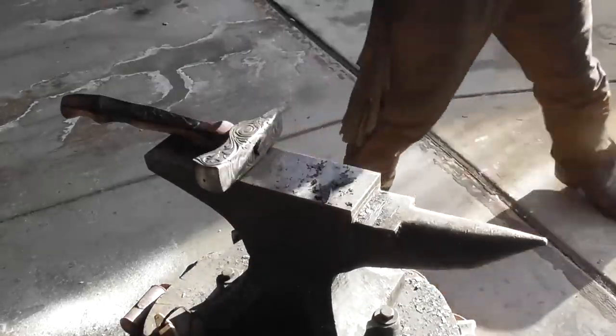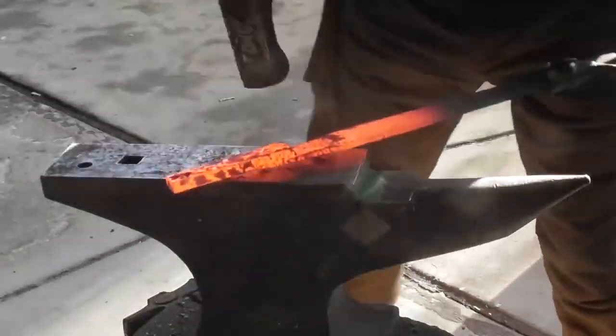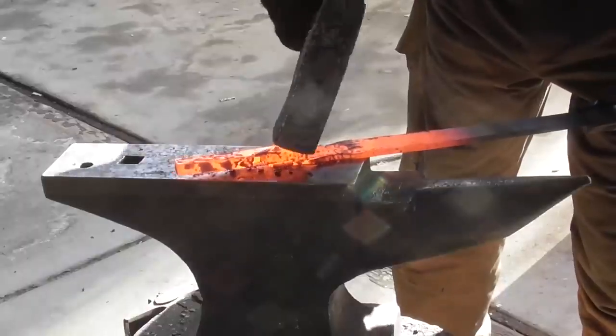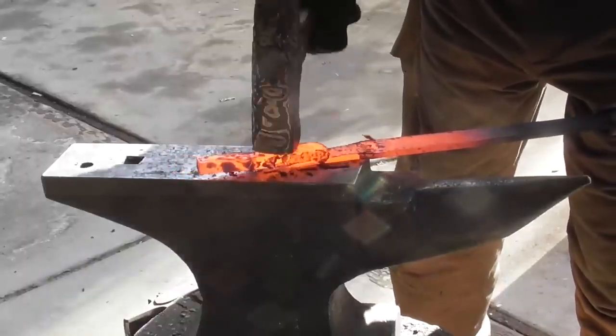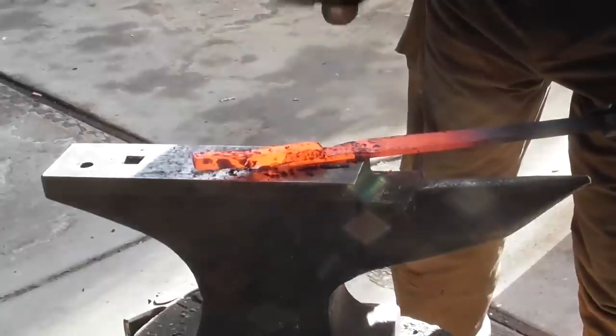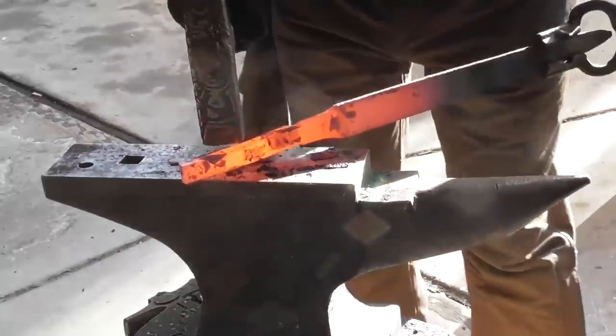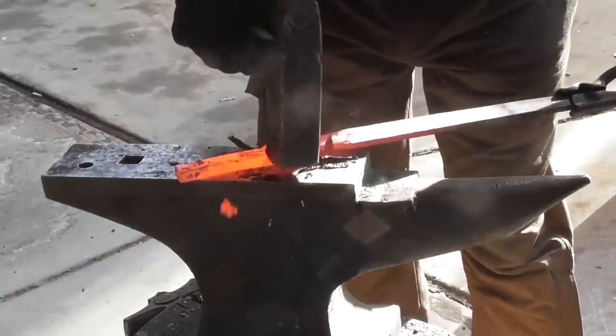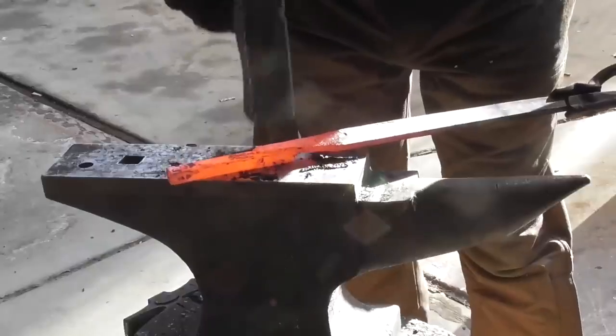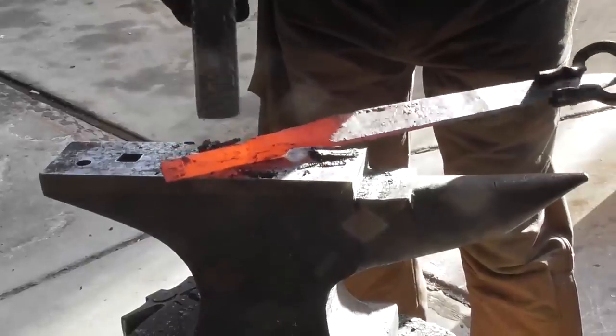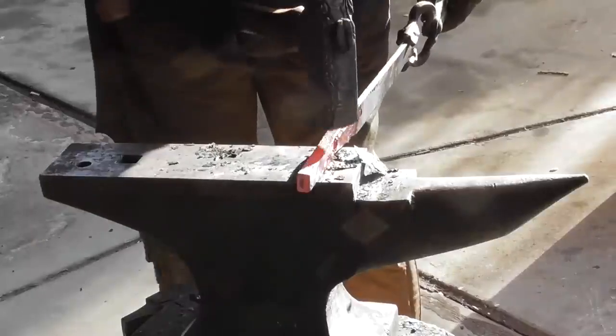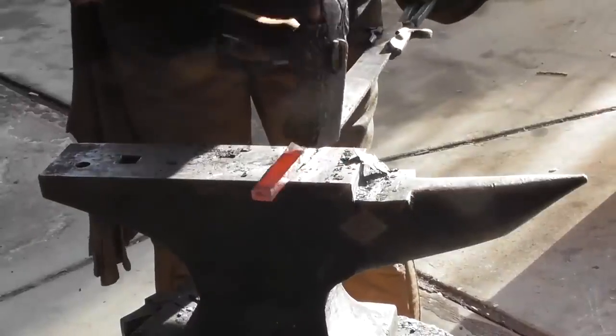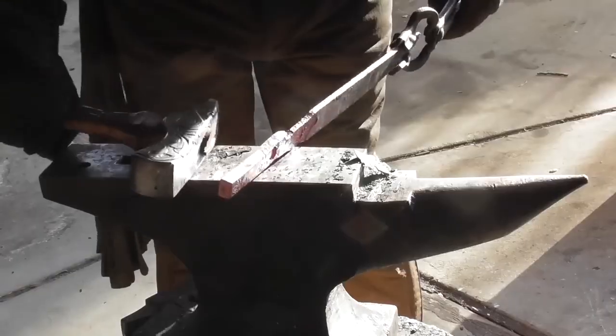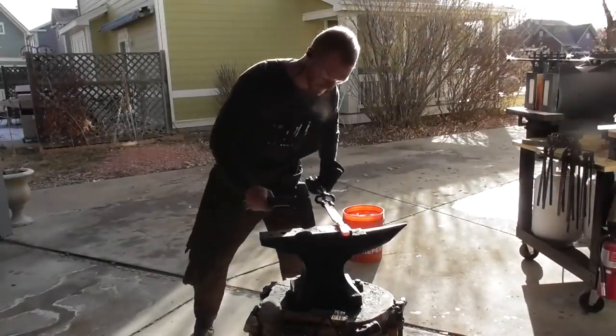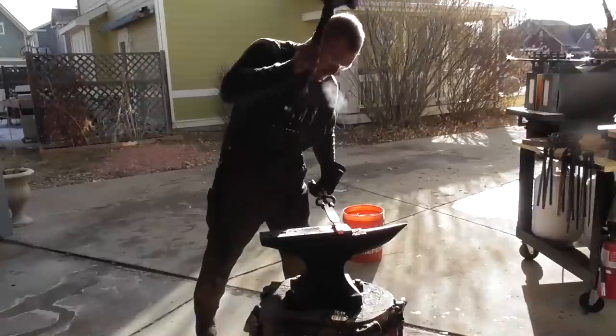Now, you can see here, I've actually probably used a little bit too much of the mild steel for the tang. I just really wanted to make sure that I had too much steel rather than too little steel. It's never fun to try and make a blade and then find out that you don't have enough steel to actually make that blade. You can see on the chunk of mild steel that I rounded it off on the end. That's so that you don't create any sharp points where you want it to forge weld, and that you'll get a nice clean forge weld between the Damascus and the mild steel.